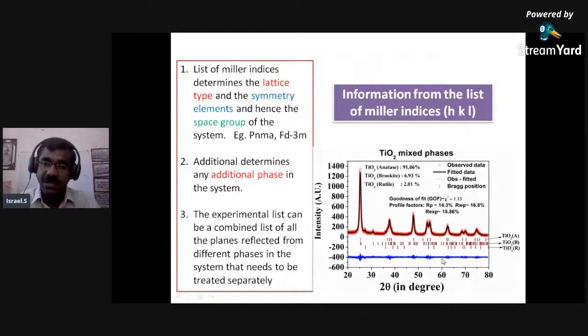Otherwise, if you leave out these two phases and look at only the anatase phase, thinking I've grown this material and this material is pure, then of course this error will be large and the reliability indices will be large. So the Miller indices can give you information whether the system that you have grown is mixed or not.